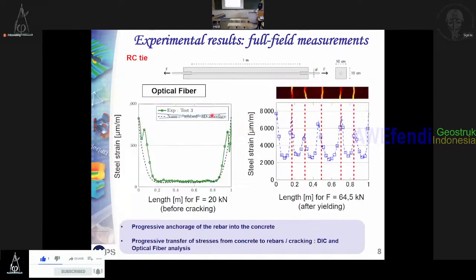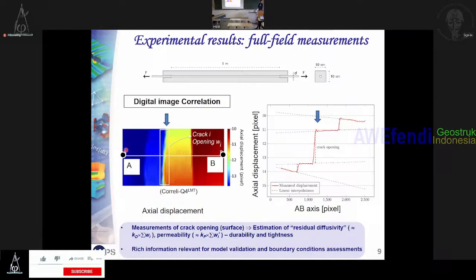With this type of technique, it is possible to access the horizontal displacement and also the vertical displacement. If you plot, for instance along this line on the surface, the evolution of the horizontal displacement, you have something linear, which is elastic, and after that you have this typical jump, which corresponds to the crack opening. So once you have the displacement field, it is very easy to access the crack opening at the surface. This crack opening will be used to find out if it is possible to predict diffusivity and permeability. I will come back to that later.